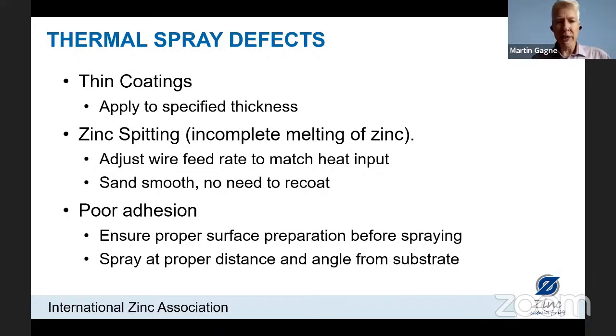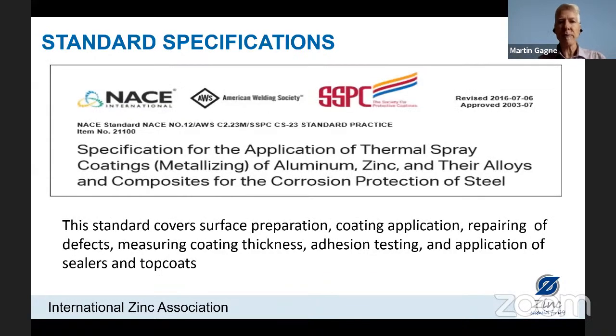And then poor adhesion. Again, the surface preparation is quite important. We must have a sharp angular profile. We must spray at the proper distance to ensure that we have good adhesion to the steel. Now, all of these topics that I've talked about, surface preparation, etc., are well documented in this standard. This is a joint standard from NACE, the American Welding Society, and SSPC. It is NACE standard number 12. It is American Welding Society standard C2.23, and it is the SSPC standard CS23.